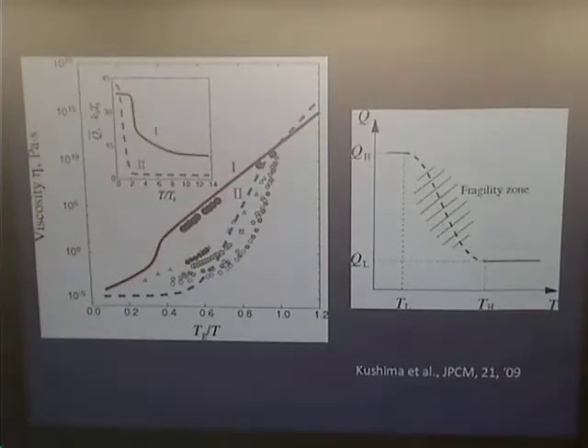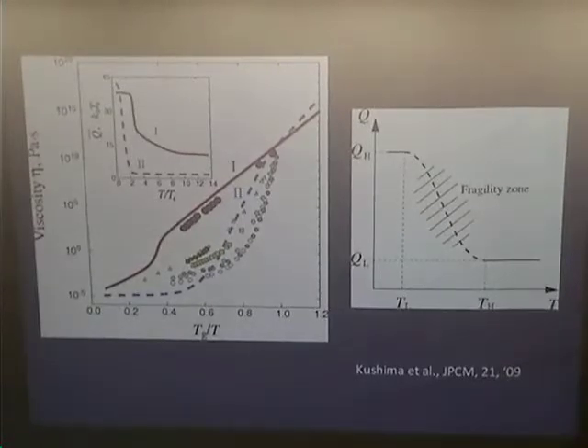Now Busch showed something in the vitreloy one, which is this multi-component zirconium-based alloy from the Johnson group. They showed data which just looks like it goes down like that, in a very narrow range, and comes up again, and that's hysteresis.